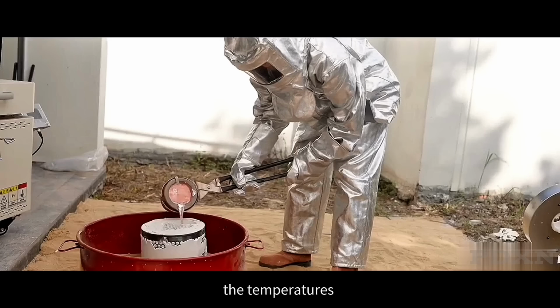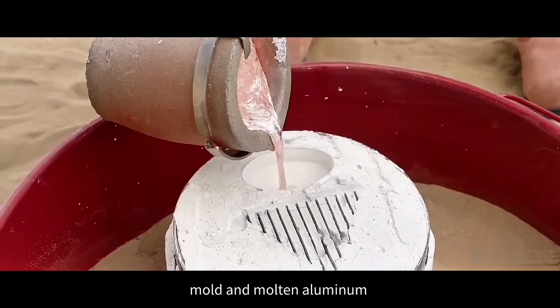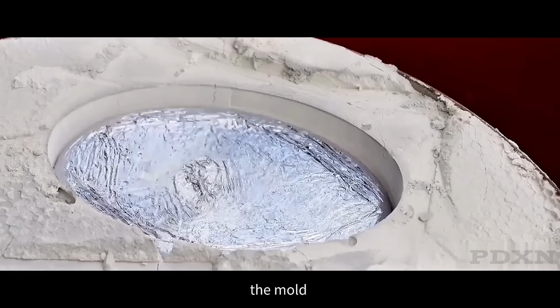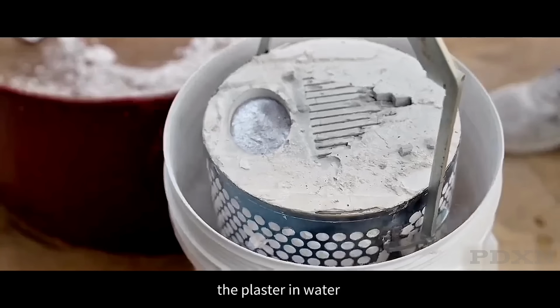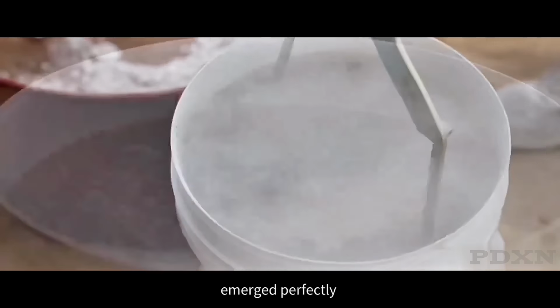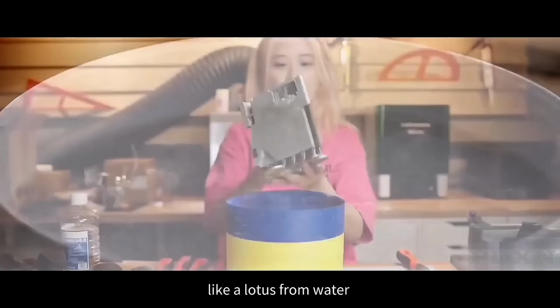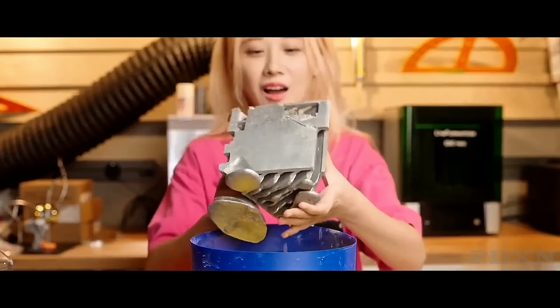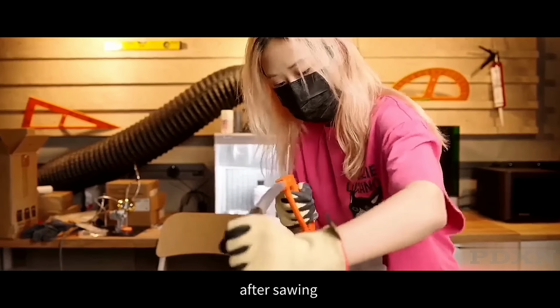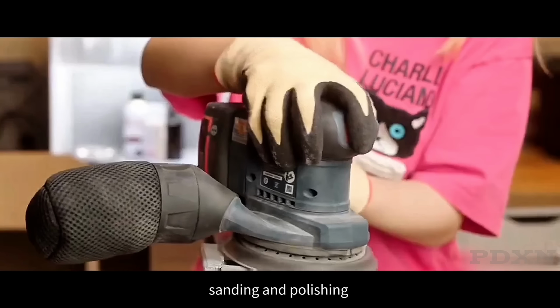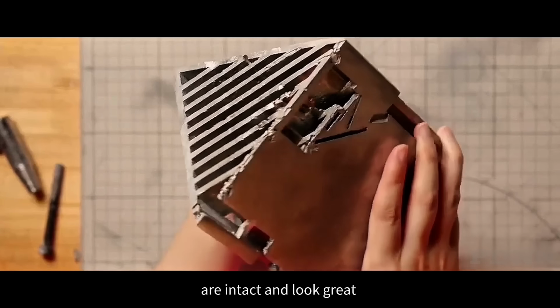I adjusted the temperatures of the plaster mold and molten aluminum. This time, the aluminum filled the mold before solidifying. After dissolving the plaster in water, the aluminum piece emerged perfectly, like a lotus from water. After sawing off the extra sprue, sanding, and polishing, the fins are intact and look great.